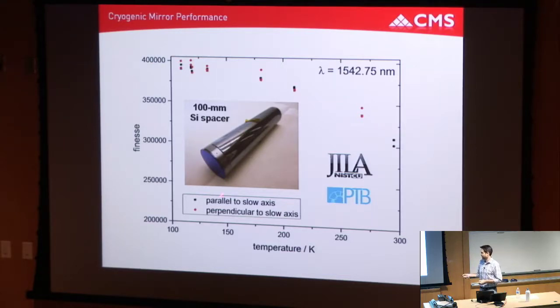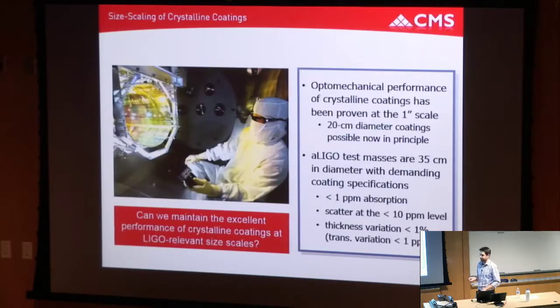So this was made to operate at 124 Kelvin, at the zero crossing in silicon. So we tuned the transmission so that it walks onto minimum transmission as it cools down to 124K. But we got very nice results, 400,000 finesse, and we're totally transmission dominated in this system. So good cavity contrast there. And very excited to see results on those cavities. Those are deployed now at PTB and JILA.